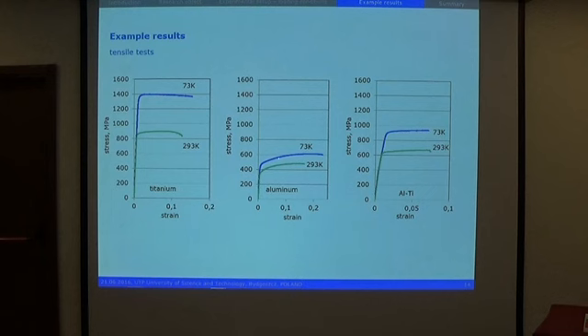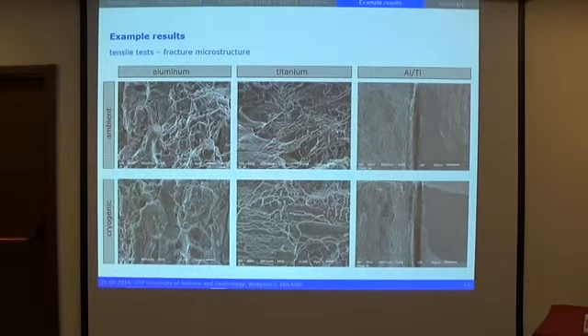For aluminum alloy, the ultimate stress also grew in comparison to ambient temperature, and a similar effect is seen for the specimen made from aluminum and titanium, the layered material. If we compare the microstructure of the cracks after the test, we can observe that in cryogenic condition we have a more brittle situation, and of course we can also observe the delamination effect, the debonding of the material as a result of the stresses which exist inside the material.